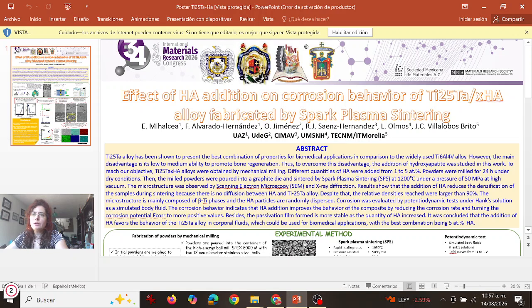The microstructure was observed by Scanning Electron Microscopy, or SEM, and we also used X-ray diffraction. The results show that the addition of hydroxyapatite reduces the densification of the samples during the sintering, and that's because there is no diffusion between the hydroxyapatite and the titanium 25 tantalum alloy. Despite that, the relative density reached was larger than 90%. The microstructure is mainly composed of beta titanium phases, and the hydroxyapatite particles are randomly displayed and dispersed.